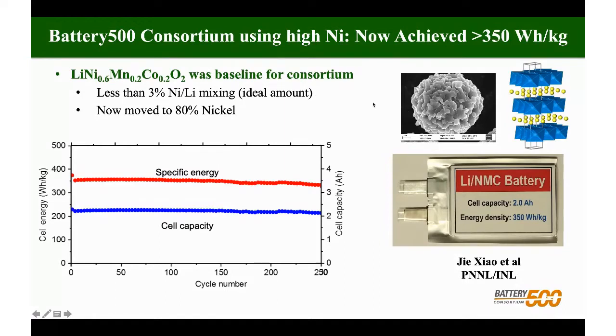So in this consortium, we all use the same material. This particular 60% nickel came from EcoPro in South Korea, and we found it to be very good. And what they did was build these pouch cells. This one is a 2 ampere hour pouch cell, and you can see they've achieved 350 watt hours per kilogram. This uses a pure lithium anode and a new electrolyte in here, and it's achieving 350 watt hours per kilogram.